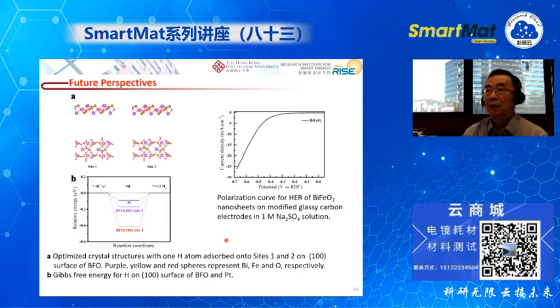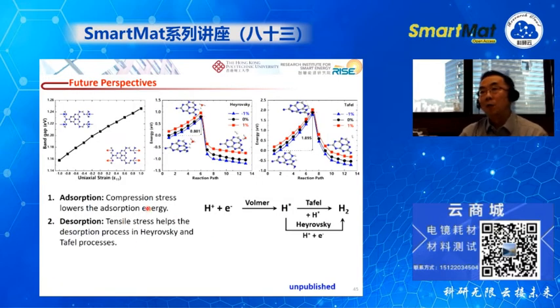So the challenging thing is how to find a suitable material with a very appropriate absorption energy in order to enhance the catalysis activity. And we also found that when we apply stress or strain, under compression stress the hydrogen absorption energy will be lowered. And during the desorption process, we found the tensile stress helps the desorption process. So how the externally applied stress will affect the hydrogen absorption and desorption process needs to be fully studied in order to understand the detailed mechanism for hydrogen generation.